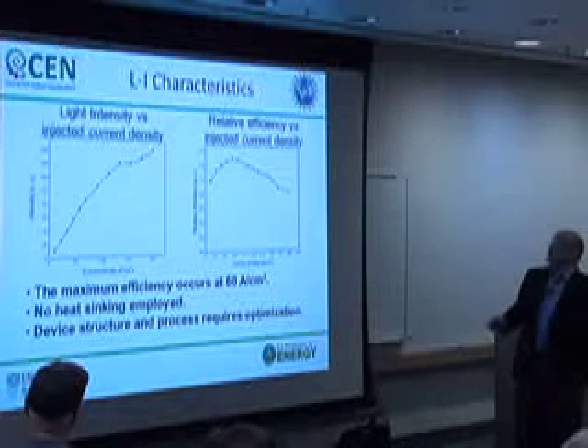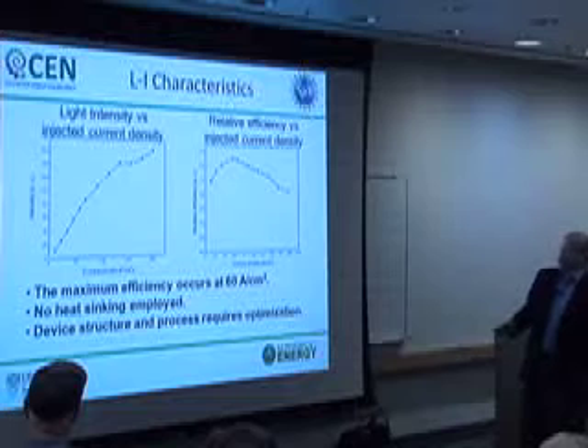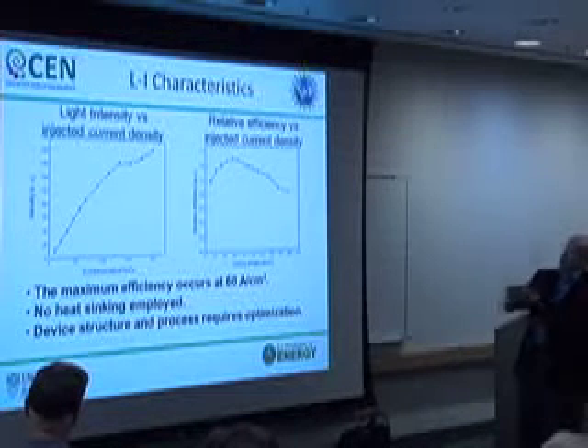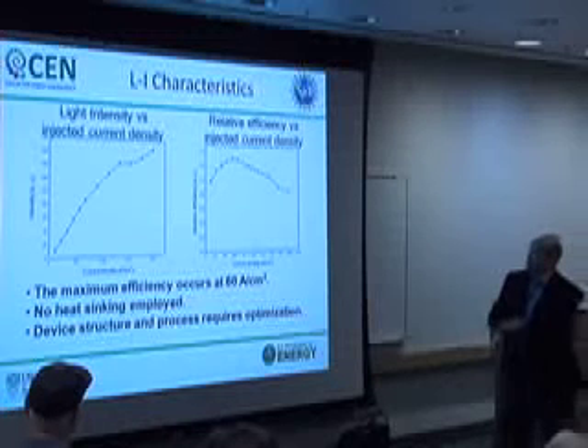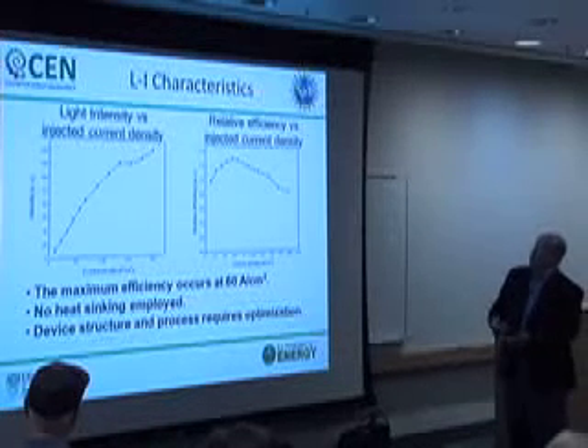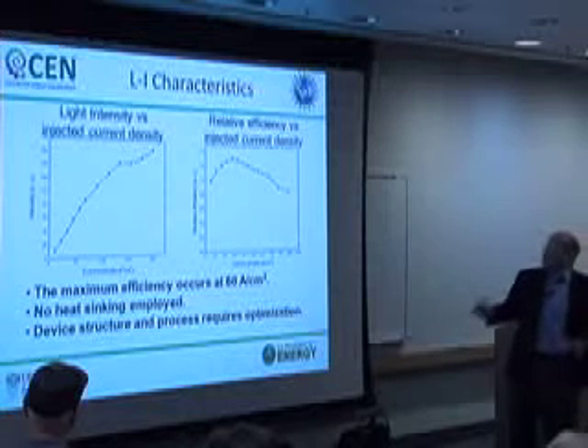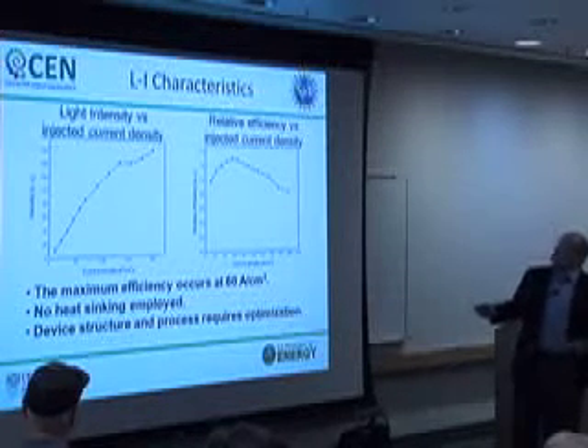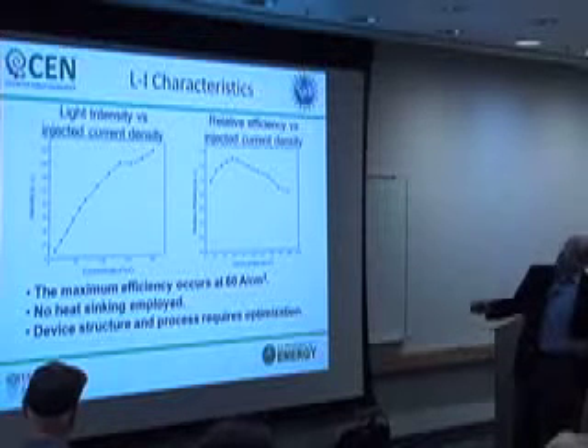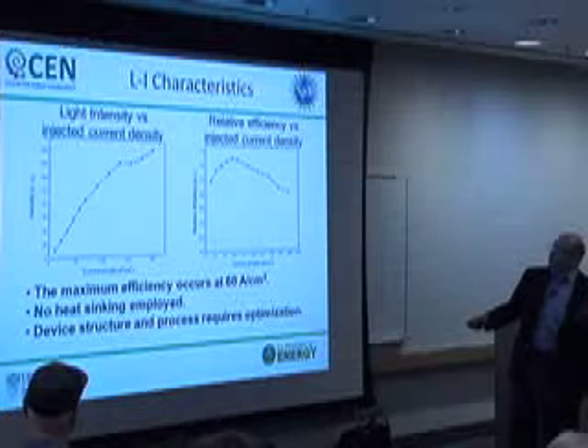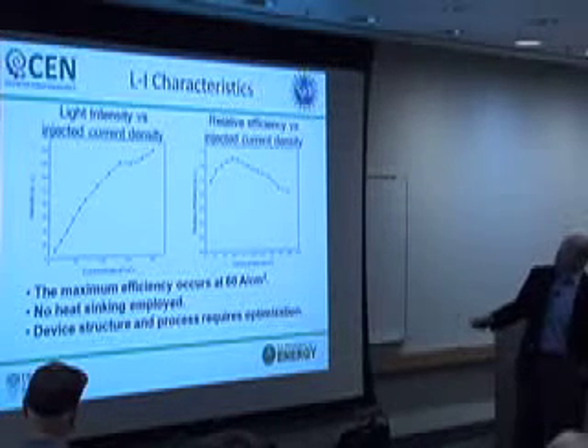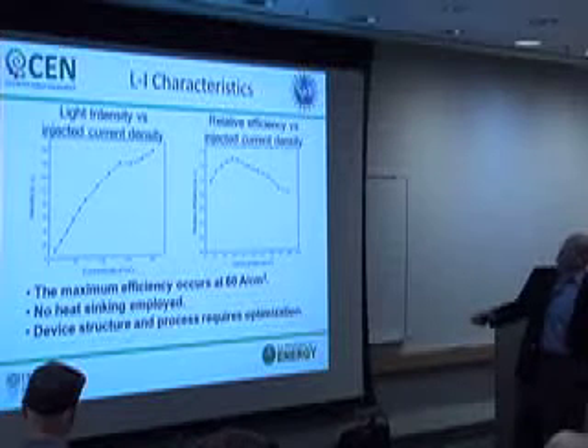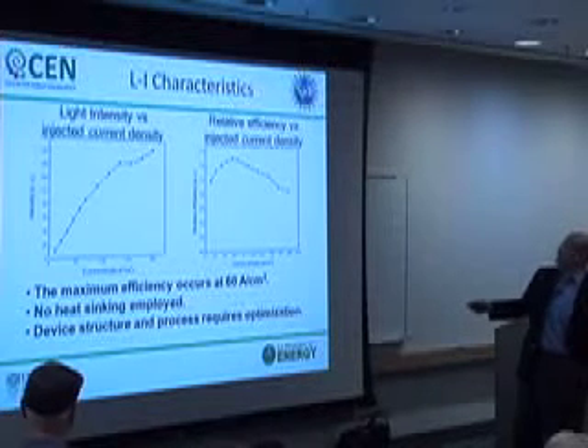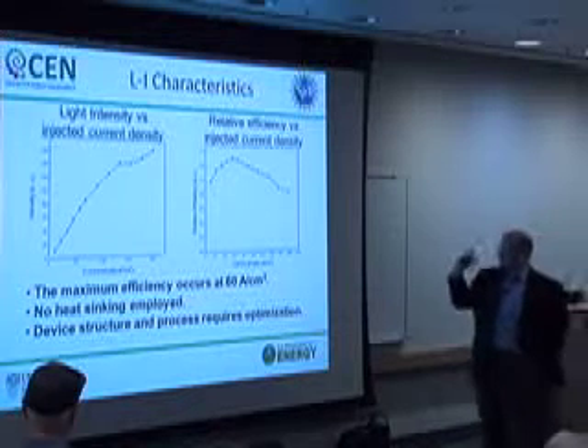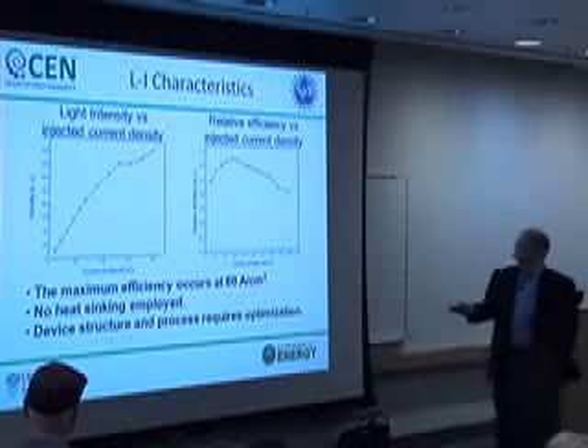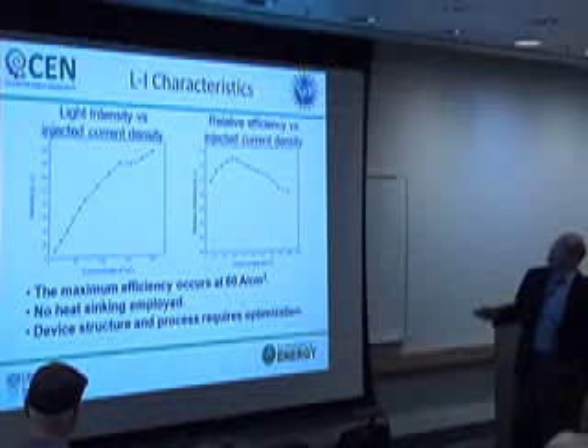The light output is a function of current density, and this is current density into the entire chip. Now, one of the advantages of these nanorods is because the surface area is increased over what you would have for a planar area, the actual injection current density into the sidewalls of the nanorod is reduced, which could be advantageous for reducing droop. Nonetheless, we're not well set up. This is done with a probe, so it's taken on a point-by-point basis, and the efficiency as a function of current shows a slight bend over and a slight amount of droop. But this is a very early device, and we hope that we'll get better data in the near future.